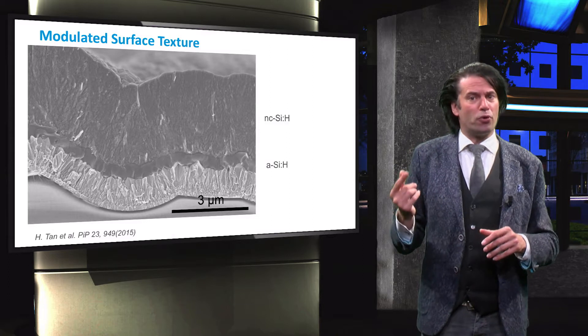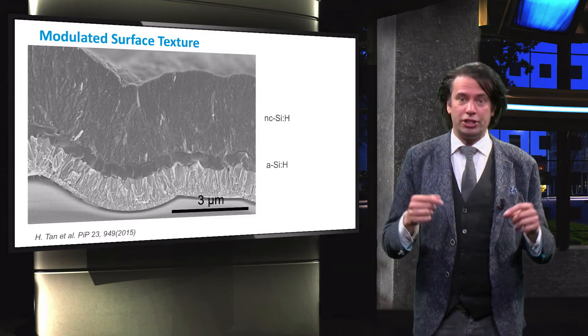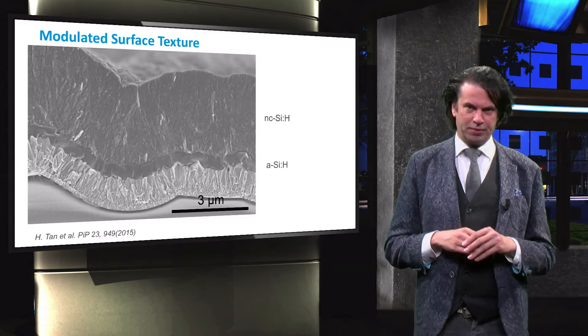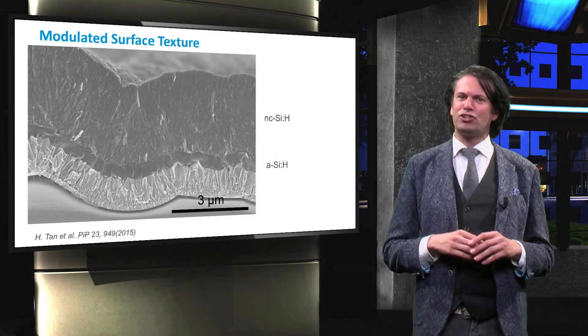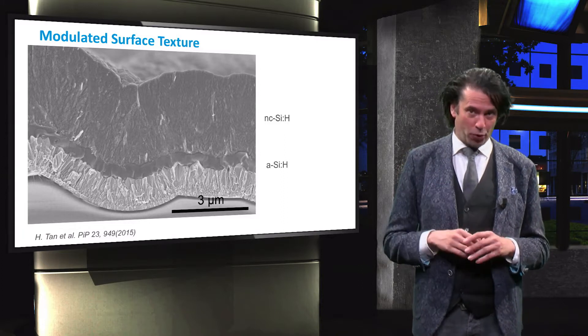Using this approach, high-efficient light trapping in combination with high-quality optoelectrical absorber materials were obtained, leading to a record initial conversion efficiency for micromorph solar cells of 14.8%.